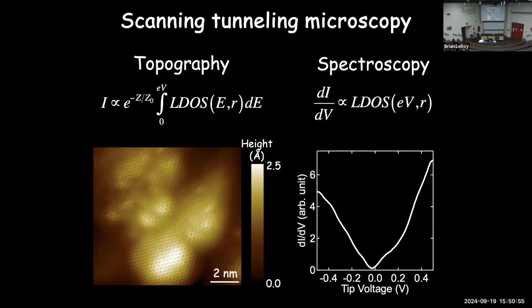And it depends on this integral of the local density of states. So basically, how many states are available for the electrons to tunnel into in the material over whatever energy range we're integrating over. In the topographic mode, we do this with a constant current. So we use a feedback circuit to keep the current constant. If this density of states isn't changing too much, then the current constant basically means that Z is being constant here. So we're basically mapping out the topography of the sample. And that's what you see here on the left-hand side, a picture of a graphene sample. The color scale is basically the height of the sample as we scan across it.